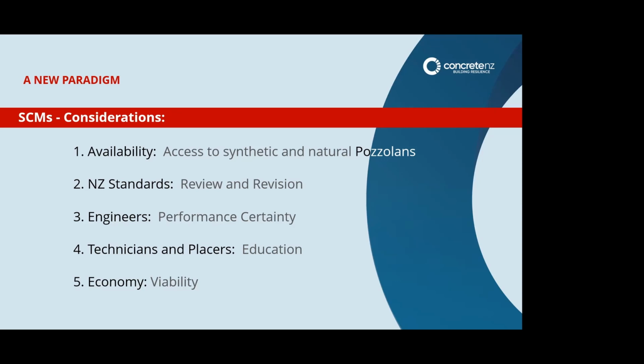And for you, obviously, you want to know that these new concretes with the cement supplements perform, that they give you the target strength at a certain time. Obviously, they cure a bit slower, so maybe 56 or 90 days is the time to achieve target strength, and not 28 days. We need to educate our technicians and placers as well, to explain to them how to best place and work with these concretes. And it must economically make sense, but this is already proven that it would. So a couple of things to